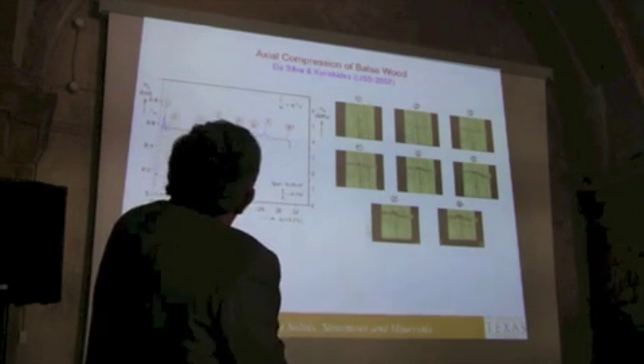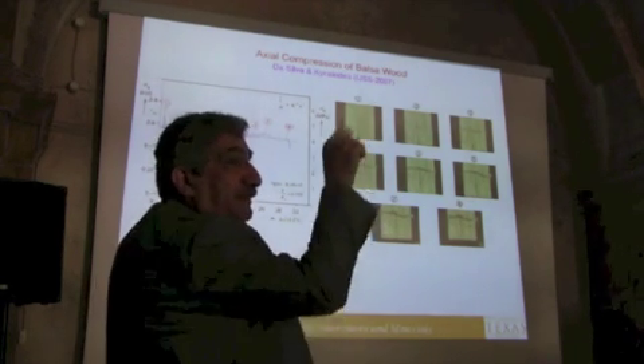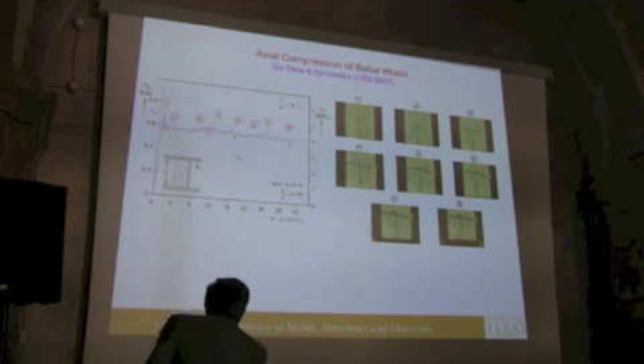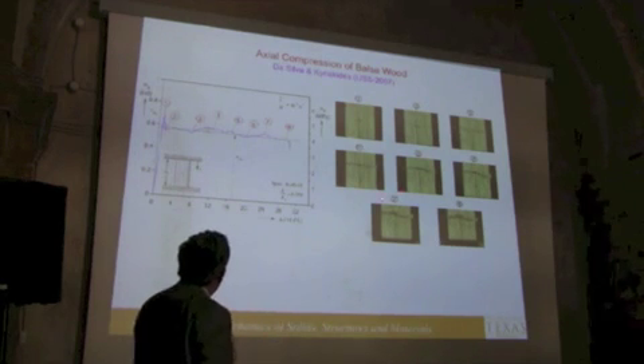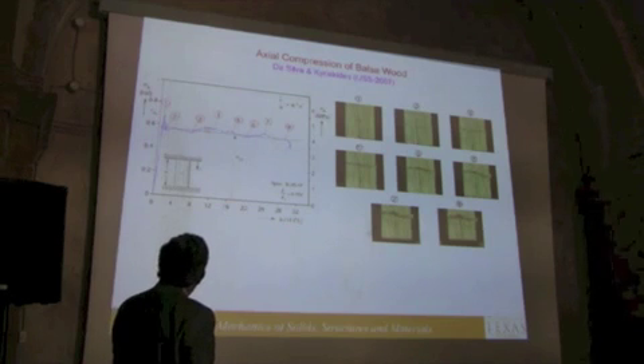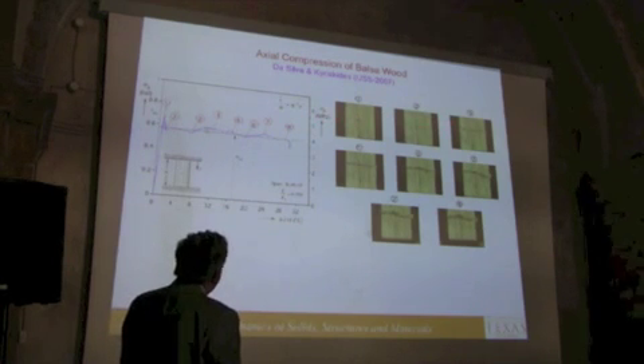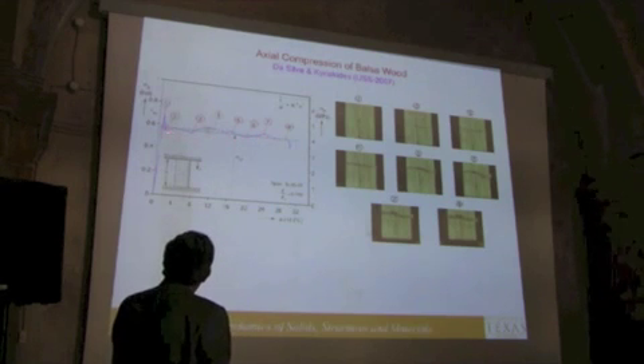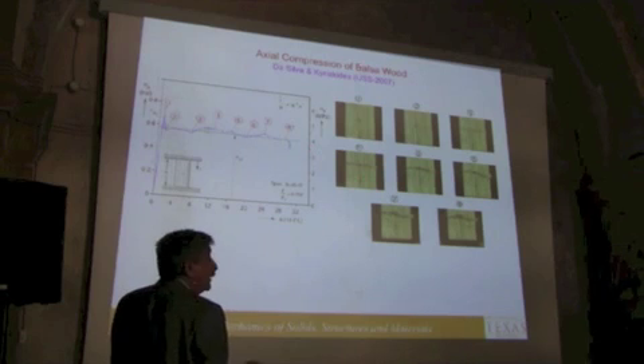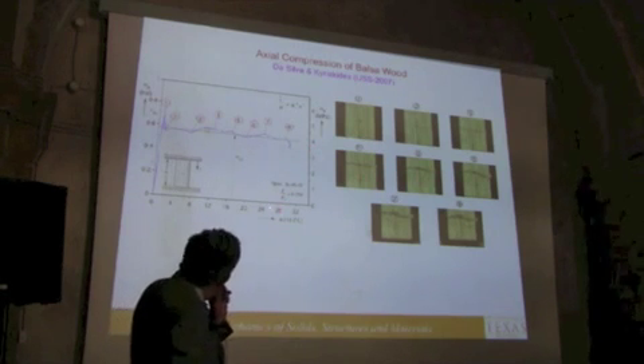So this is some more recent experiment from one of my master students, French master student for those that are interested in nationalities. And what it is, balsa wood is that lightweight material. The fibers are aligned this way. We compress, okay, stress, change in length. And what happens is that there is a failure. I'll show you what the failure is in a minute. And then you see this extended plateau, and it continues. And if you manage to crush all of it, then it will go up. Now, this specimen, I cannot even read it myself.